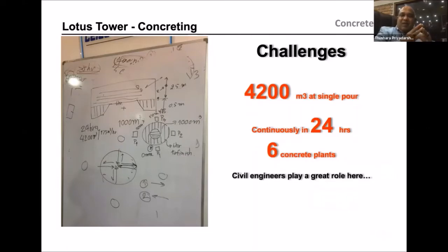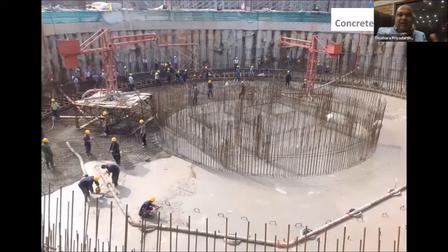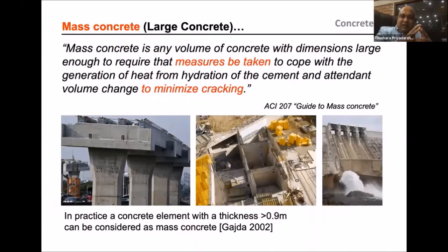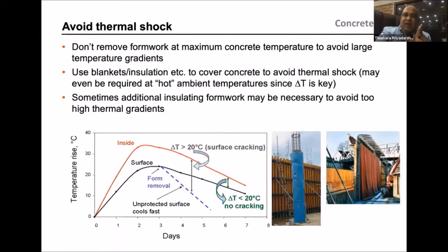Shiromal, all involved in this structure. This is where you need to be really worried about heat of hydration of the main foundation area. So for large concreting or mass pouring, mainly we have to consider two things. One, the maximum temperature of the concrete should not go beyond, say, 70, 75. And the temperature gradient should be at the level of 20 to 25. Otherwise, there will be a lot of issues.